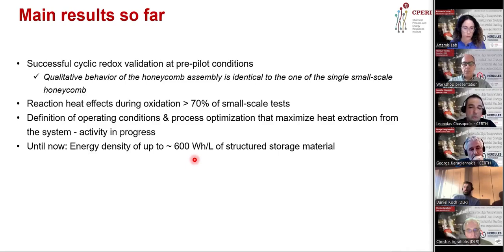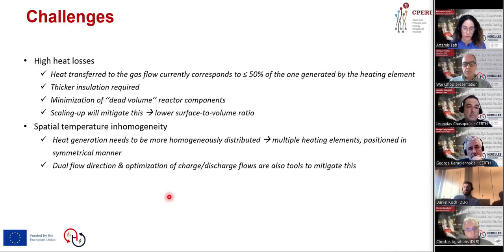This confirms also the material's capability to store and release the heat effectively over the multiple redox cycles. Next slide, please.